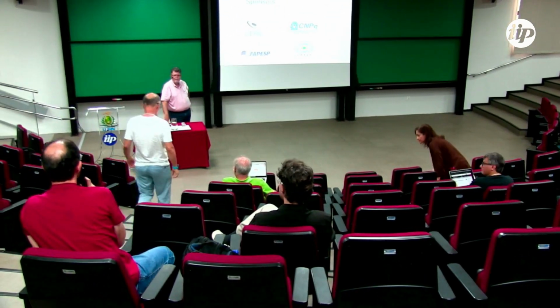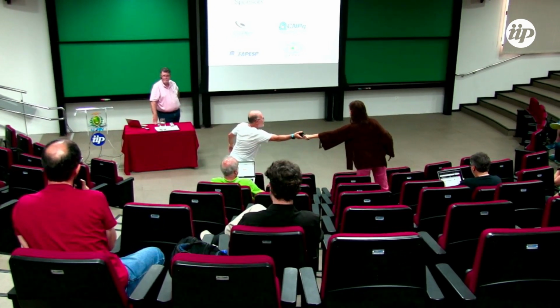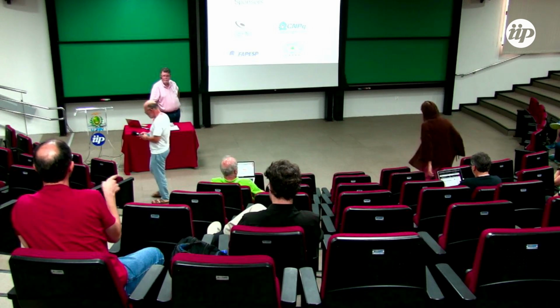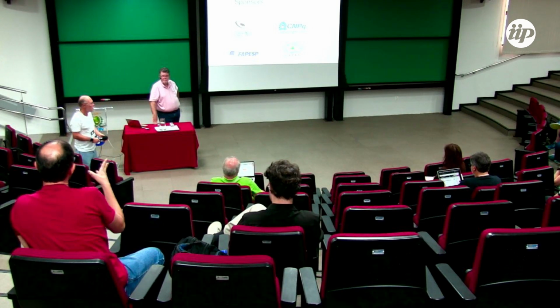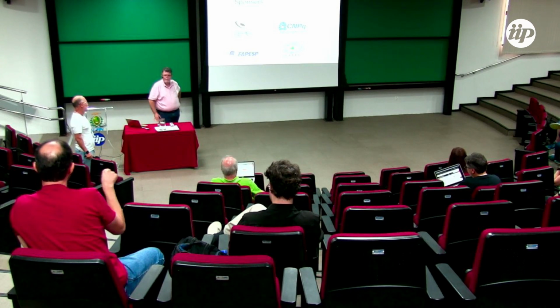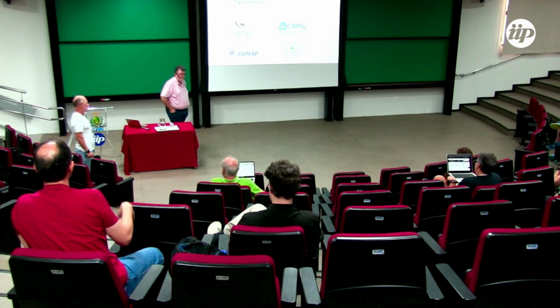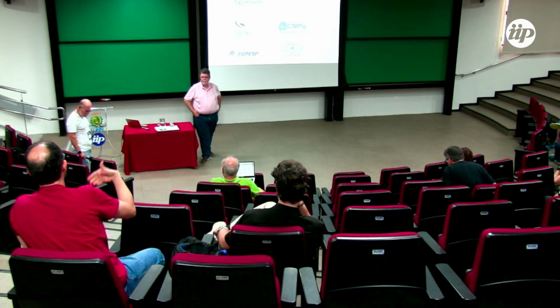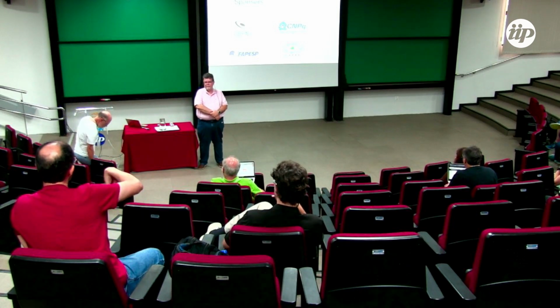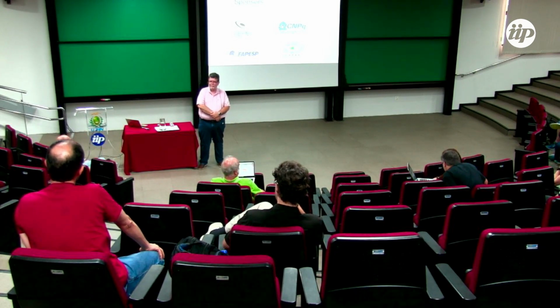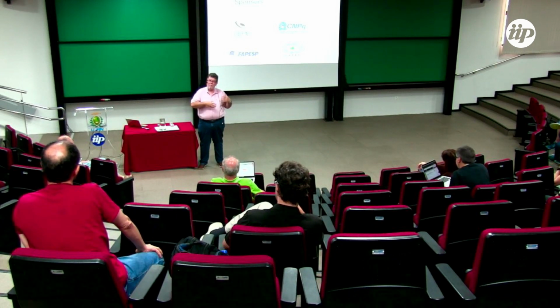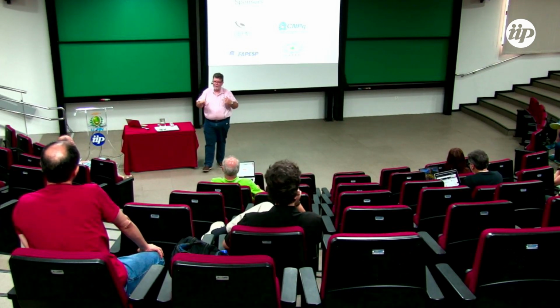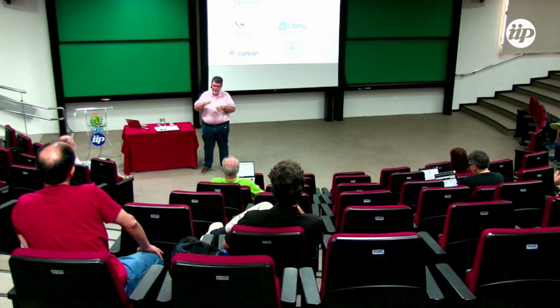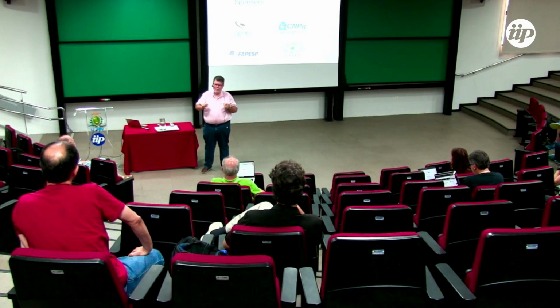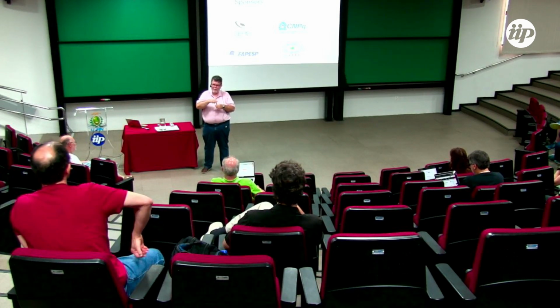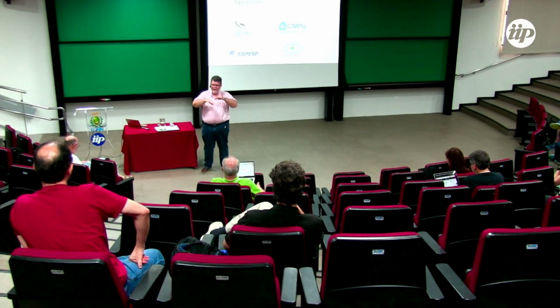I have no idea how simple this could be from the experimental point of view, but if you have a time-dependent magnetic field, did you try to look at how the susceptibility responds for different frequencies of an external magnetic field? This could provide you some insights about the dynamical behavior of your spin waves. Yeah, the problem of the metal samples: when applying an AC magnetic field, it induces eddy currents in the sample. And the eddy currents produce a magnetic signal. I see. And the